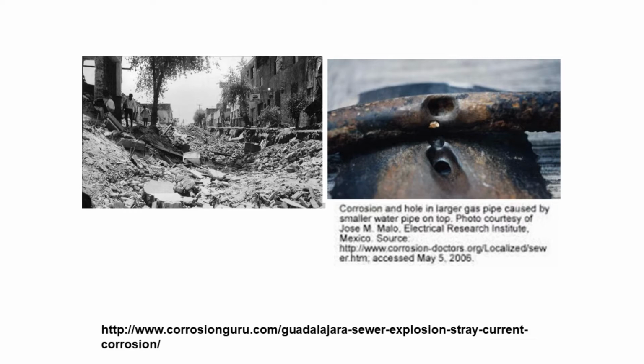So this large hole in a high-pressure water pipeline then produced a jet of water, which you can see blasted over the petrol pipeline. And so in turn, the petrol pipeline was worn away, probably by a combination of the jet, its erosive action, and the corrosion caused by the water getting onto the petrol pipeline.